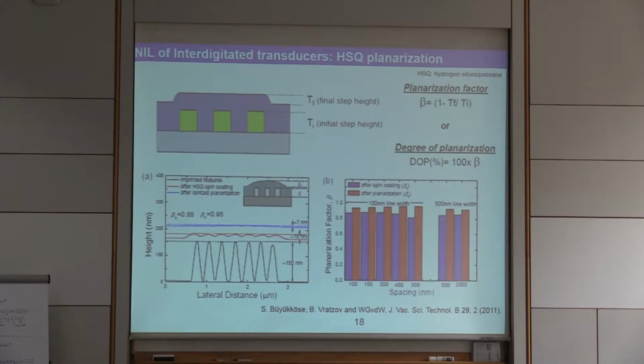result there? If you have the planarization factor defined as follows, you look at the initial step height of your features, which in this case are on the order of 150 nanometers or so, so these imprinted features, and you compare that with the planarization after just spinning on. You see that, of course, this is already far reduced, but still in the order of 10, 20 nanometers. But if you now do this flat wafer imprint, you can really get to sub 10 nanometers. The figure of merit there is the so-called degree of planarization, which after this pressured flat wafer is close to 1, both for 100 nanometer scale features, but also for larger scale half micron features or so.